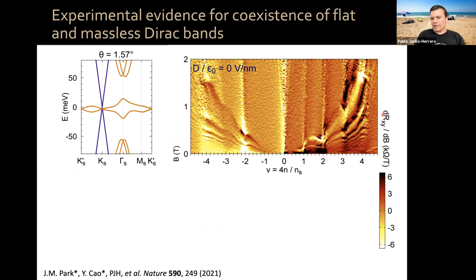So if you measure Rxy as a function of density, filling factor, and as a function of magnetic field, and you take the derivative, you can see that we have a set of features, these vertical features occurring at each integer. Those are the magic angle twisted bilayer graphene-like part, which exhibits the analogs of the correlated insulator features at each integer. And you can see riding on top of this thing, this parabolic-looking thing, which has ups and downs. What you're looking at there is the chemical potential of twisted bilayer graphene measured by the